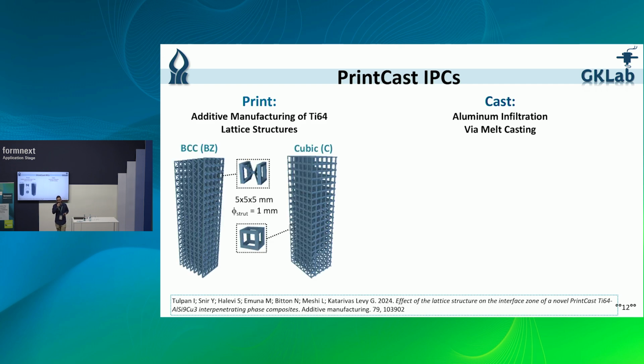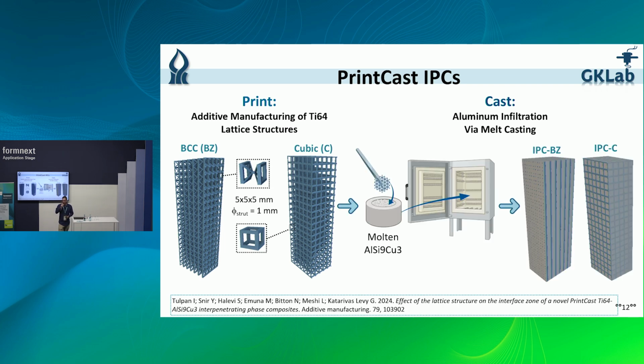First, we 3D printed lattice structures out of a titanium 6-4 alloy. And then we infiltrated the pores of the lattice structure using cast aluminum alloy in a high-temperature environment. The resulting IPCs combine the properties of both constituent materials as well as of the lattice structure.